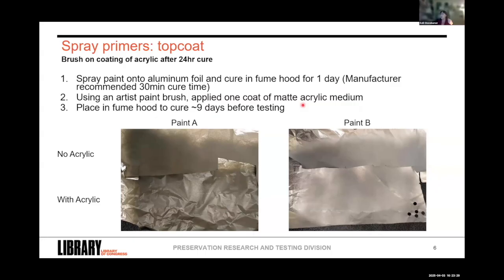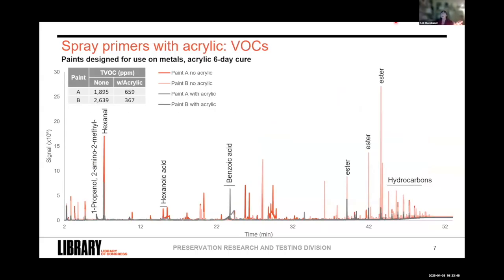You can kind of see some of the gloss here on these bottom samples that have the acrylic medium compared to the no acrylic on the top. These did get a cure for a little bit longer before going through the volatiles and Oddy testing. Starting off with the volatiles testing, immediate difference with that top coat on there for both paint A and B that are in the gray lines. We're going from thousands of part per million of compounds down to the hundreds, much more ideal.